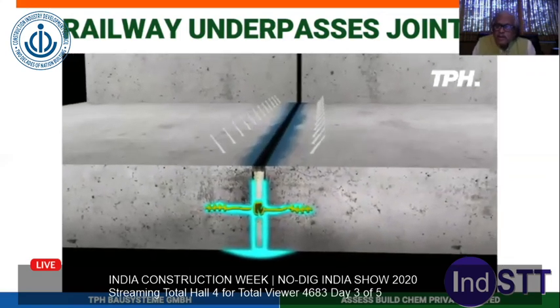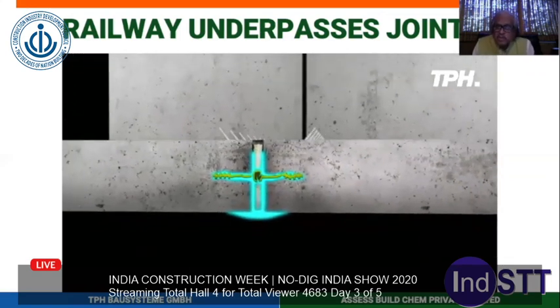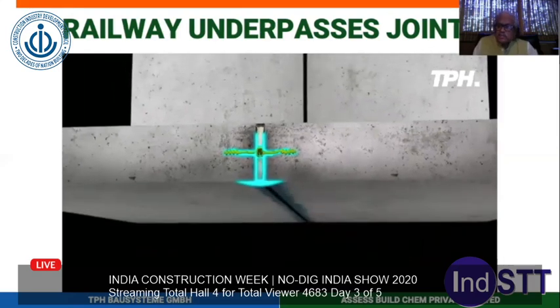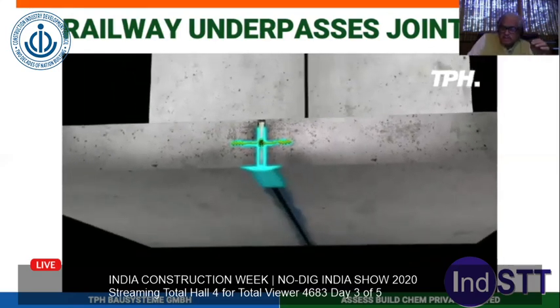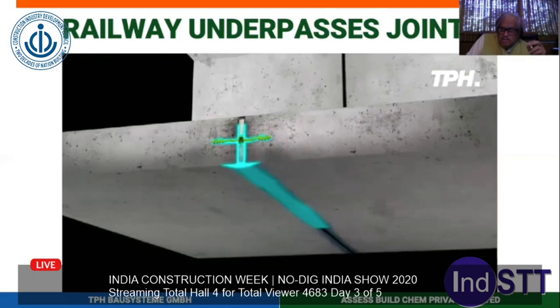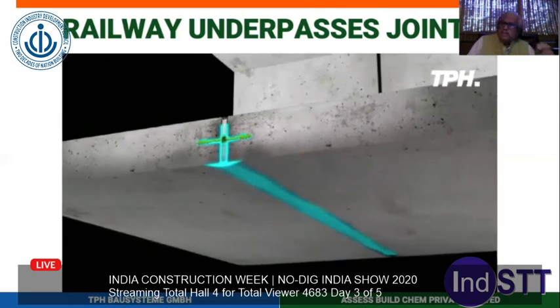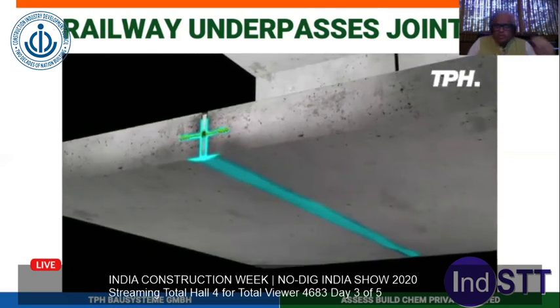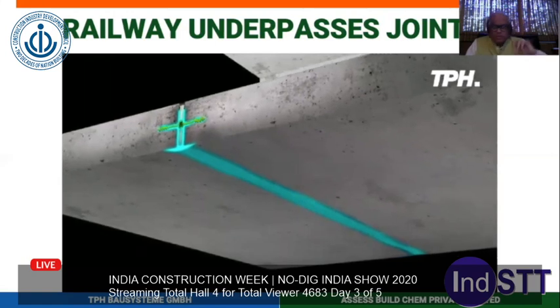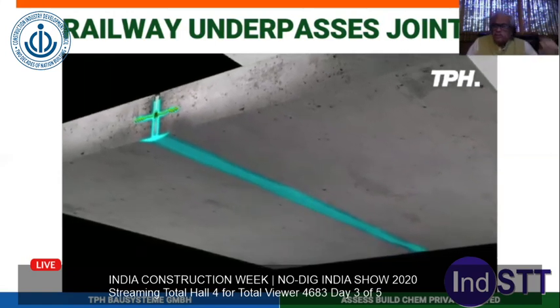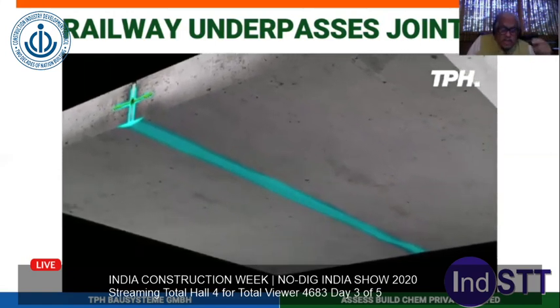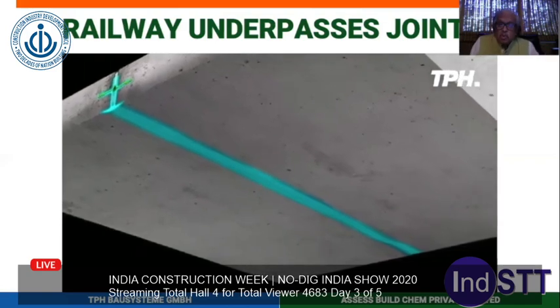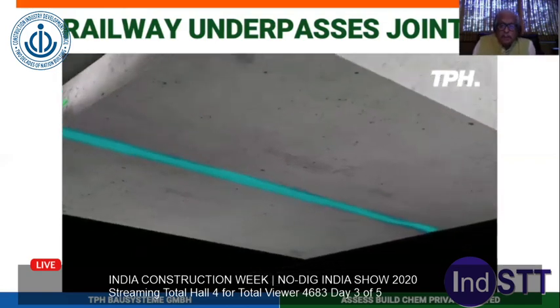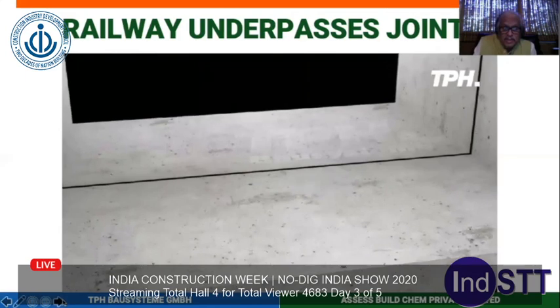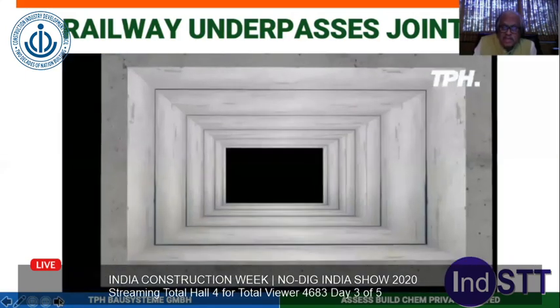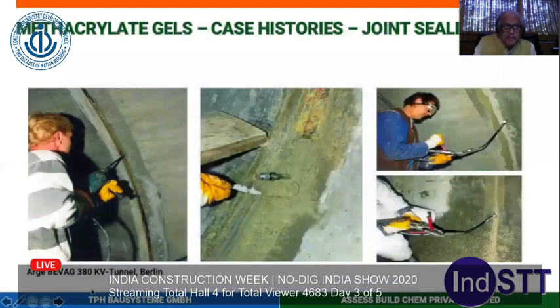So over a period of time, when you use the gels, you inject. You can see it is such a simple process. It's a single step process. You make this simple one step process into a 4-step process or 5-step process, or put some injections inside, put some foams inside. Okay, you can still put some foam inside to stop the water initially, but permanently what is important is a gel which will set inside.